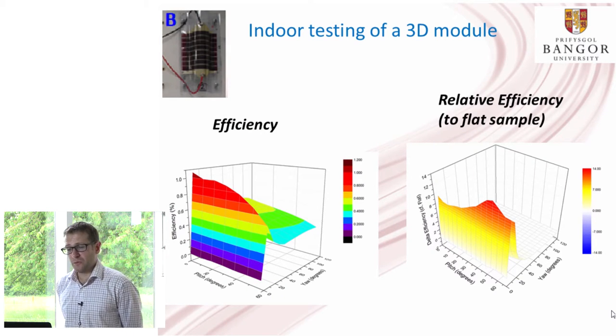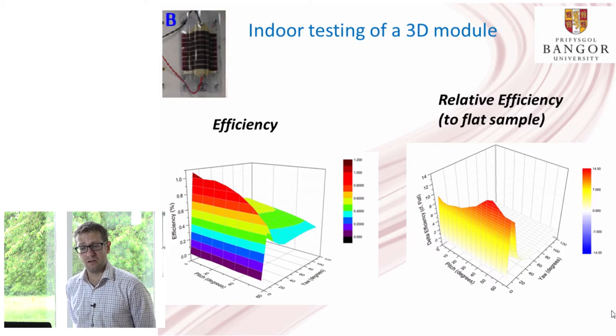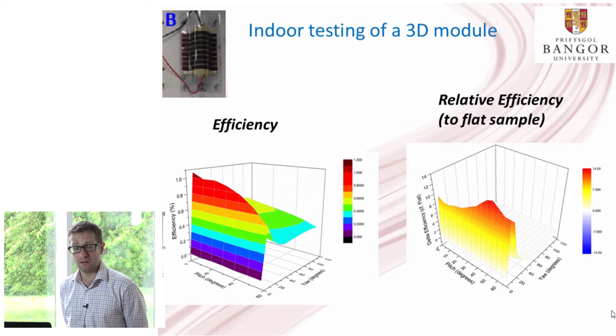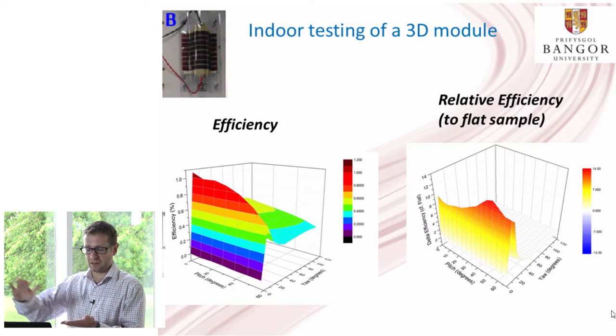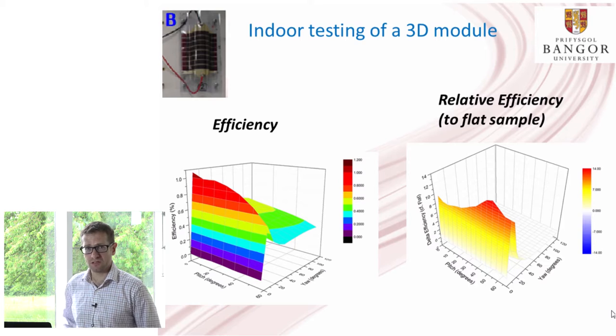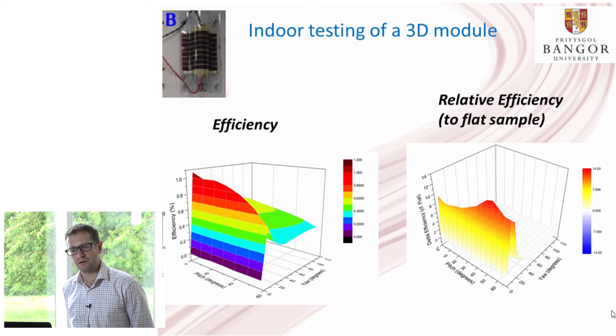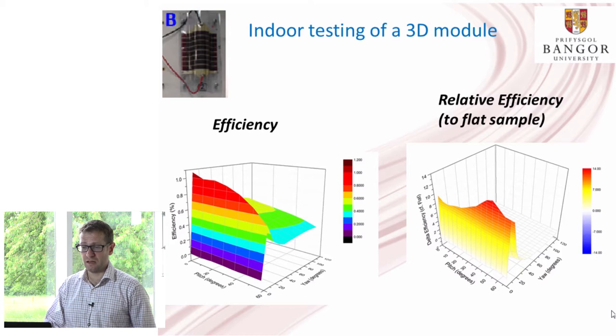When we take our best performing module, module B, we find that the performance of this solar cell exhibits a really big increase in efficiency at low angles of incidence. Whereas a flat module tends to reflect light coming in at low angles of incidence, with this three-dimensional configuration we're able to capture a lot of that light and boost the efficiency. The efficiency increases by almost a factor of 10 at low angles of incidence. So we get quite substantial increases in solar cell efficiency at oblique angles.